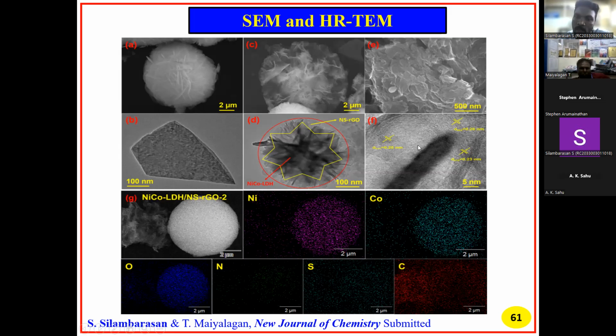The particle size is confirmed by the calculation as 0.26 nanometer. The plane is 002, and 0.25 nanometer and 0.23 nanometer confirm the nickel cobalt LDH with the NSRGO sample 2. Then the elemental mapping of nickel, cobalt, oxygen, nitrogen, sulfur and carbon, all these elements are confirmed in the HRTEM analysis.